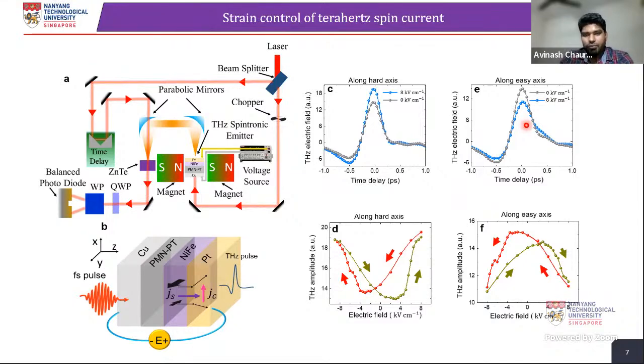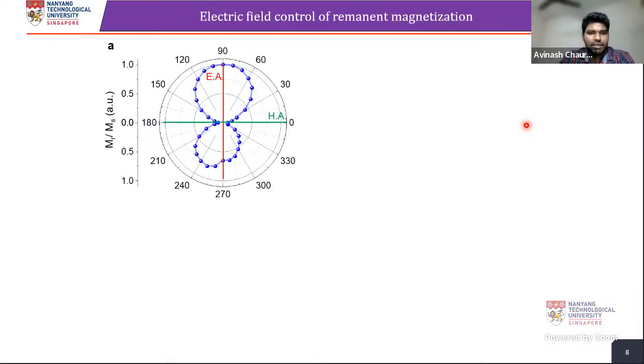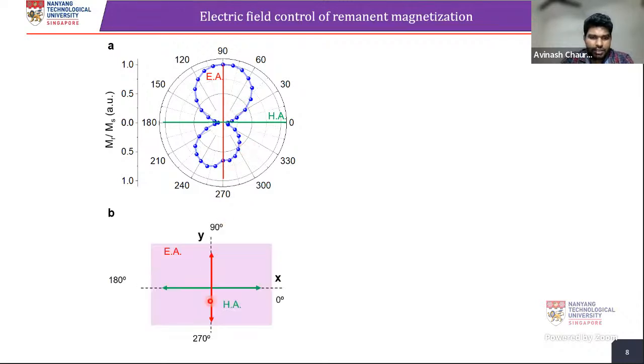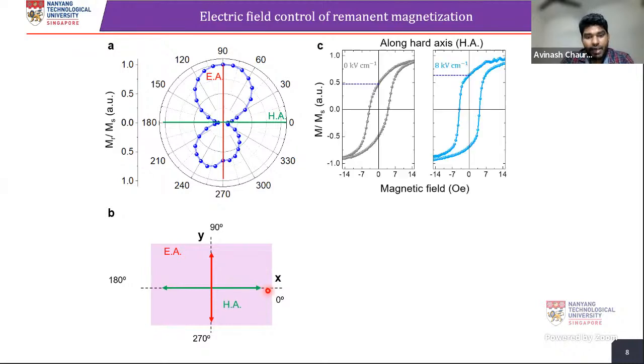So for that, we did the VSM measurement by rotating the sample. So this is the normalized remnant magnetization with the rotation of the sample. So by rotating, we can see the change in the remnant magnetization of the ferromagnet. So from here, we can find the easy axis and hard axis of the material. So easy axis along this direction and hard axis along the other. So what we do, we set the sample in this direction first, and then we apply the electric field.